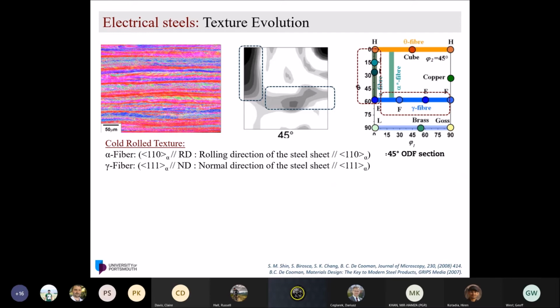However, in simple terms, if you have a BCC unit cell and you push it under this high strain rate at that low temperature, the 110 or 111 plane don't have much choice but to align: the 110 aligned with the rolling direction, and the 111 direction aligned with the normal direction, because basically you're just crushing all the lattice, and they don't have much choice but to align themselves under that huge strain rate.